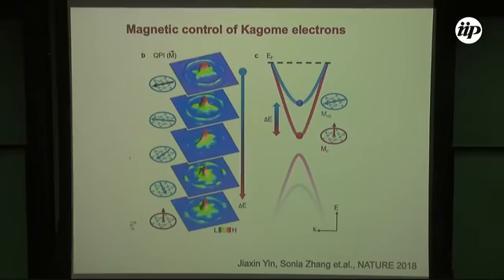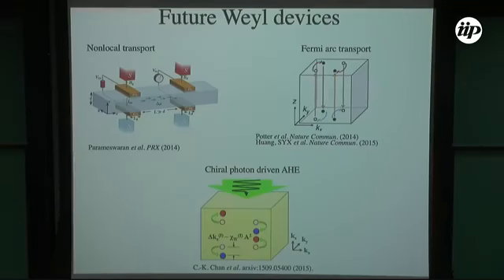So there's another puzzle about this system. As I showed, in the 2D Chern magnet or topological magnets, if we apply a field, then the gap opens, and the larger the field, the larger the gap, right? Here we see that there was a gap in the unperturbed material, a gap in the ground state band structure. And then when we apply a field, we see that the gap is actually decreasing with the applied field. So it has this additional twist. This is something we don't fully understand.